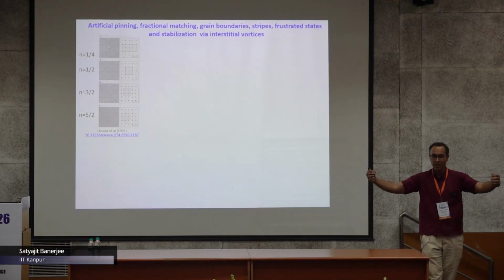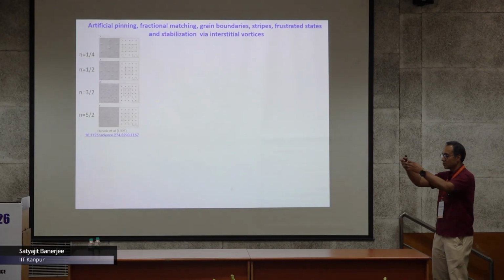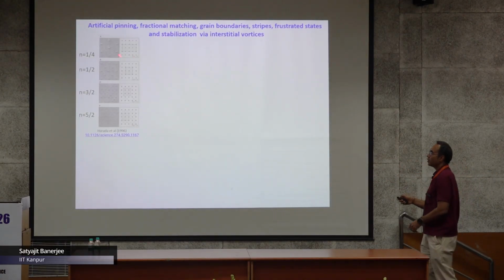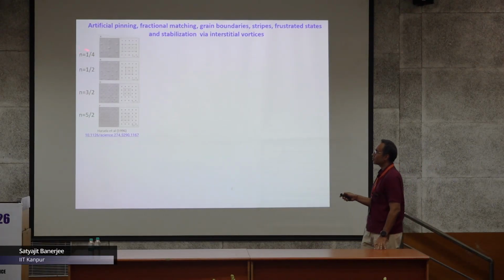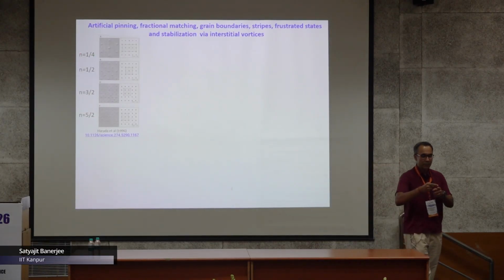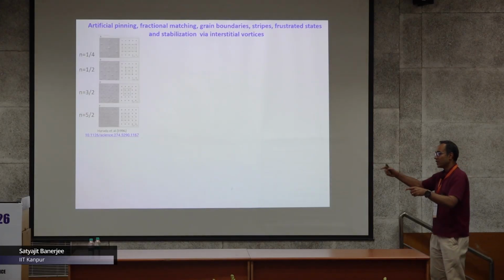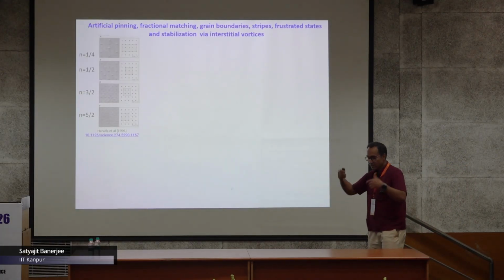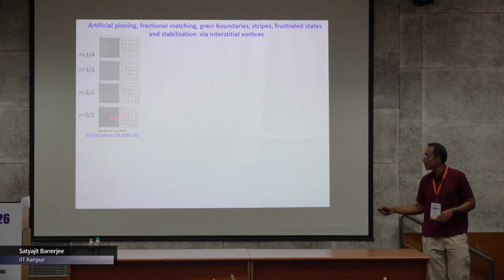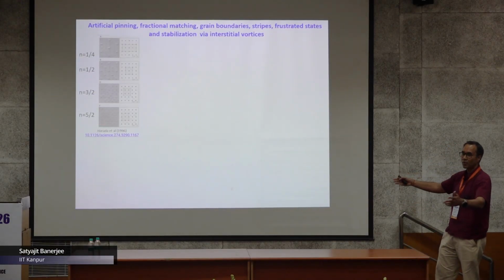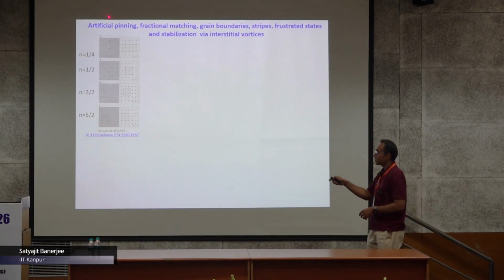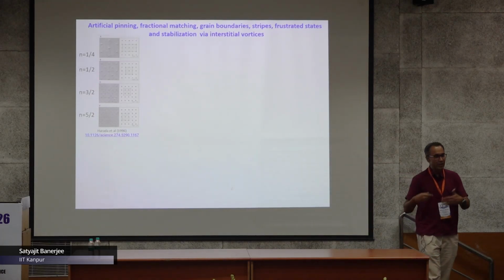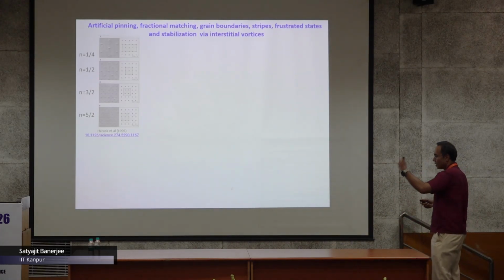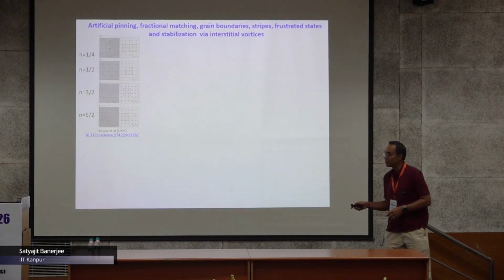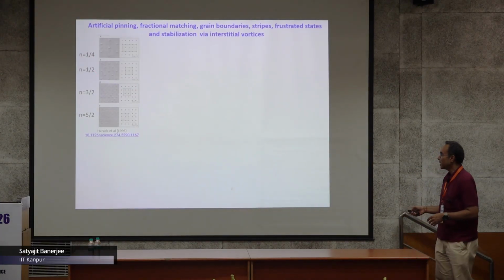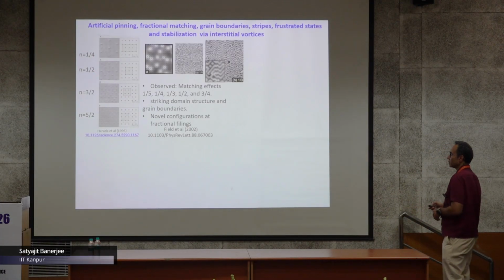You have a periodic array of holes, and vortices which have another period, and each of these steps corresponds to fractional filling. For example, there's one vortex per every 4 holes at a certain magnetic field, and as you increase the field, you get 2 vortices per 4 holes, giving sub-fractional filling. You can keep increasing it, moving through different commensurate states, observing various sorts of fractional filling states in the system.